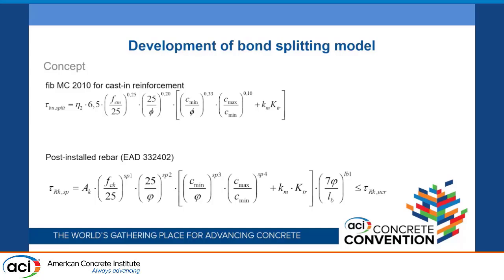The concept which we developed at that time, which is now in the European assessment document 332402, was to take this approach and transfer it to the post-installed rebars, which means we need a prefactor, let's call it A. Then we have normalization to the concrete strength, so we need one exponent. This is 0.25 currently in the fib code, and we call it a product-specific exponent. The same applies for the rebar diameter and the concrete cover, and we have the transverse reinforcement, which should have a similar influence. And then we also have the influence of bond length, which is accounted for in the fib Model Code also, but through a different equation.